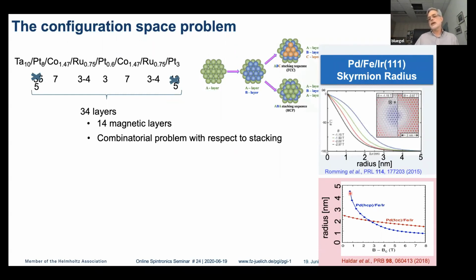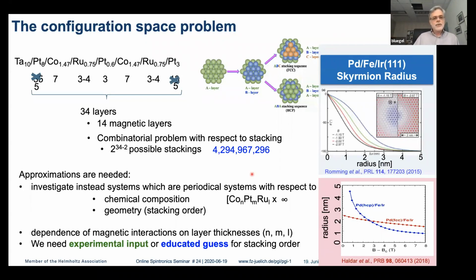You see here the Skyrmion radius for iron on iridium with palladium stacked HCP or palladium stacked FCC is quite different. So if you would calculate all possible combinations of HCP and FCC, you have easily a few billion stackings. I'm a great fan of high throughput computing, but this is a little bit too much. Therefore, we have to think about either getting information about experimental input or educated guesses for the stacking order in order to progress here. So any information is extremely welcome.